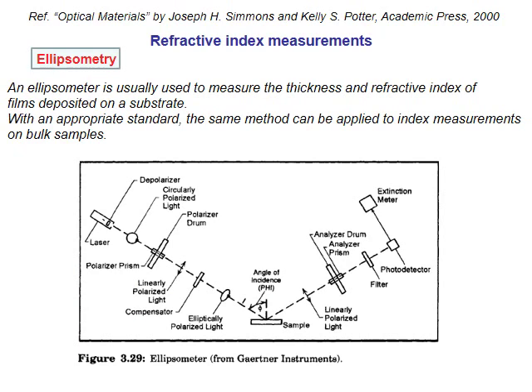An ellipsometer is usually used to measure the thickness and the refractive index of films deposited on a substrate. With an appropriate standard, the same method can be applied to index measurements on bulk samples. This is the general scheme of an ellipsometer.